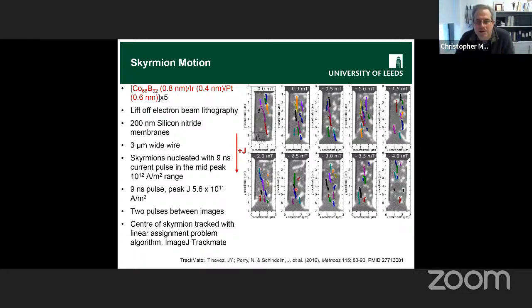So you can see a couple of things. First is that many of these skyrmions move down the wire in the direction of the conventional current flow. Electrons are flowing from bottom to top, conventional current is flowing from top to bottom. That makes us believe that it's spin orbit torques which are causing the motion. And you can also see that as well as moving down the wire, they tend to drift to one side, in this case the right-hand side, more often than not.